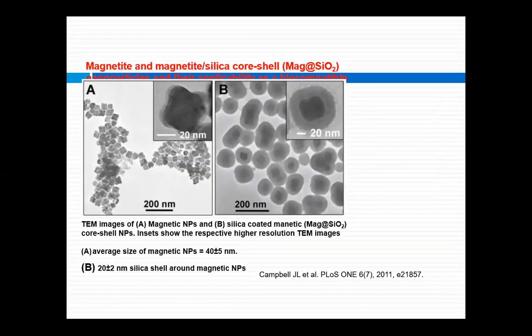Okay. So this core-shell structure you can find out from the TEM. XRD cannot give this clearly. What is the thickness of the coating? It may give, but you have to be careful. At lower magnification, it is difficult to find where the core is and where the shell is. So the top inset is shown at higher magnification. That is the image taken by a high resolution transmission electron microscope. You can see clearly the darker and brighter regions. So you have to make the judgment where the coating is. You can measure the thickness. In this case, it is around 20 nanometer.